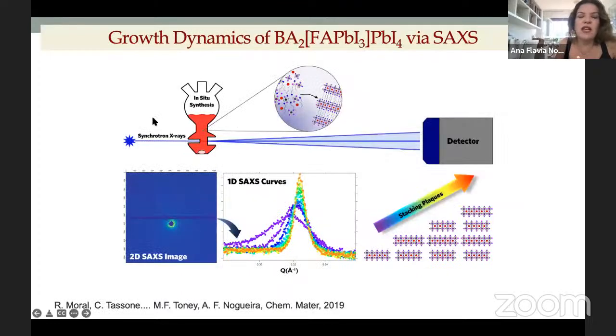So basically, we are using synchrotron X-rays. This is our chemical vessel here. So this is the image that you can get from this experiment. This is a 2D SAXS image. Of course, we're doing a lot of treatment on this in order to get what is familiar for us: intensity versus Q. Remember that Q is related to theta.